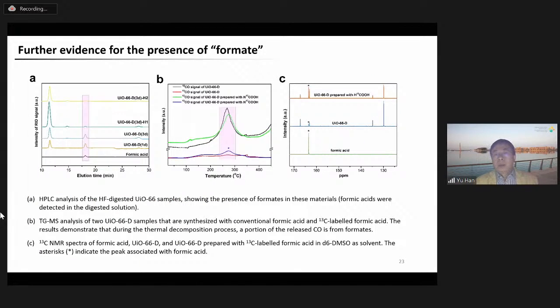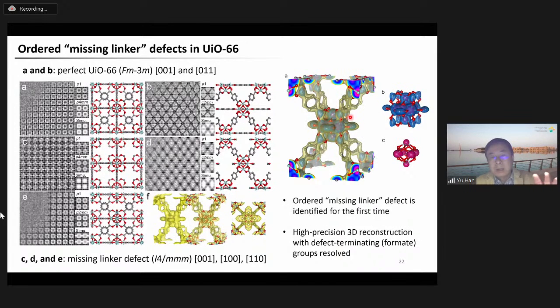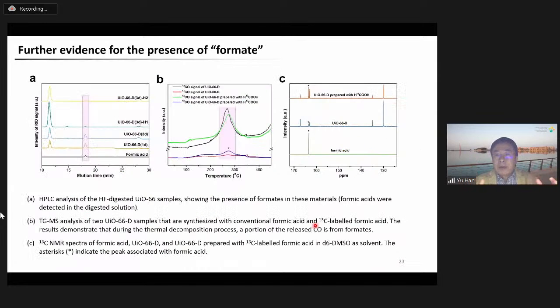And to confirm this result, we use, oh sorry, I forgot to mention. We can see not only the missing linker defects, but more importantly, we can even identify the defect capping groups. The defect capping groups are formate groups. And to confirm that the defective sample contains formate groups, we used carbon-13 labeled formic acid for the synthesis. And then we characterized the sample using HPLC, TG-mass, and carbon NMR. And all these characterizations indicate that there are formate groups in the defective UiO-66.